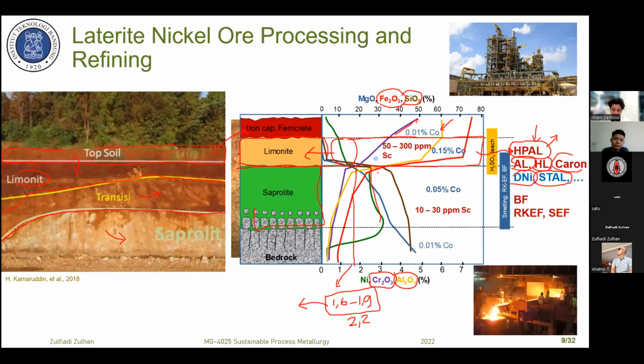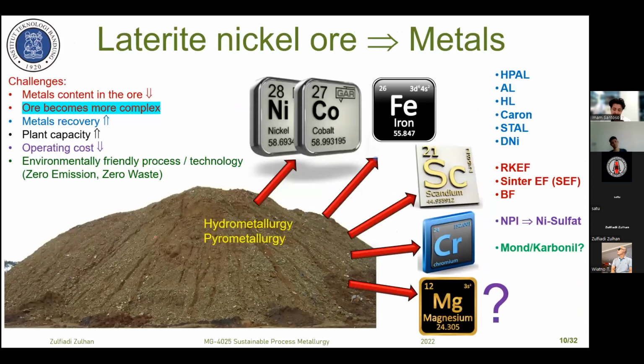And the iron content is less than 30%, in the range of 10 to 30%, and it has a high content of magnesia and also a high content of silica. The cobalt content is also less compared to the limonite layer, and the scandium content is also less compared to the limonite layer. Okay, this is the type of nickel ore.